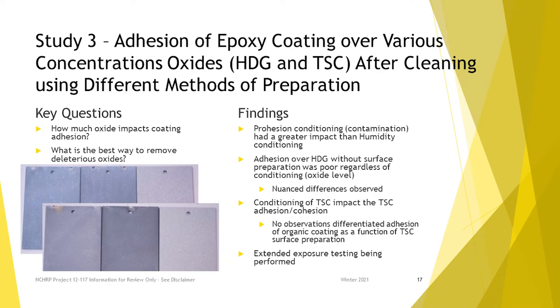Study three is kind of the keystone of this whole thing. We basically took four different metallic coatings, aged them three different ways, then applied any of nine surface preparations, and then applied the duplex coating on top. Without getting into all the details, of all those combinations, the only problem we had was painting over zinc galvanizing that had weathered without receiving any surface preparation. The galvanizing industry has known this for years, so it was not a surprise — it was actually good that it failed, because that's what we expected. All the other combinations did very well, with all these different surface preparations working.